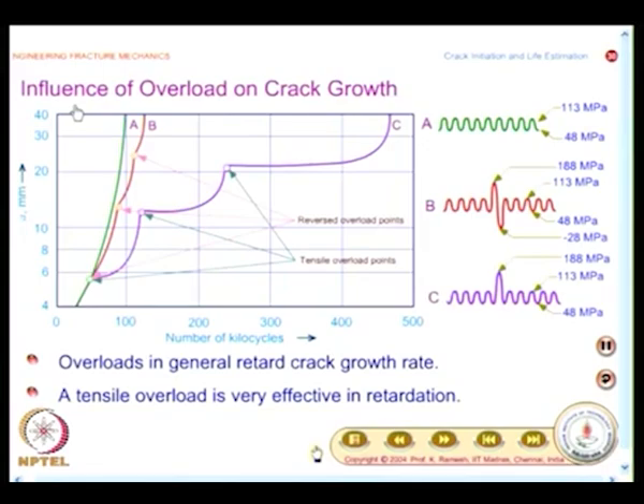Again, he will go back to the basic kernel of how Paris reported dA by dN, there would be modification to that which will accommodate the effect of overload, and this is very important in the fracture literature, influence of overload on crack growth. So, in one graph you see for the constant amplitude how is the crack growth, for a reversed overload how does retardation take place, for overload in one direction the retardation is quite significant.